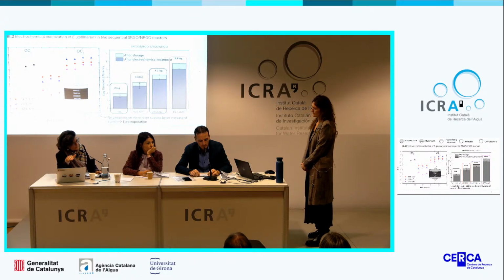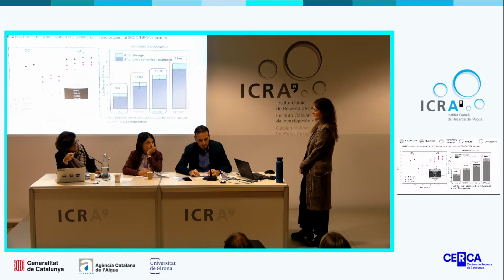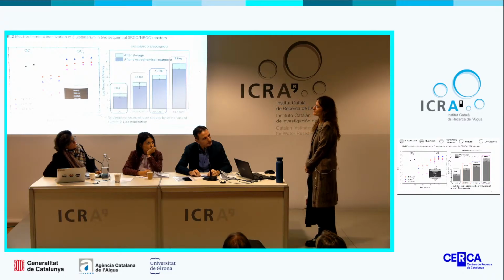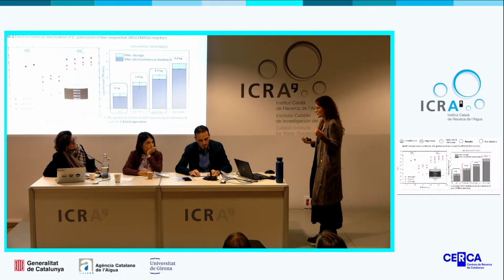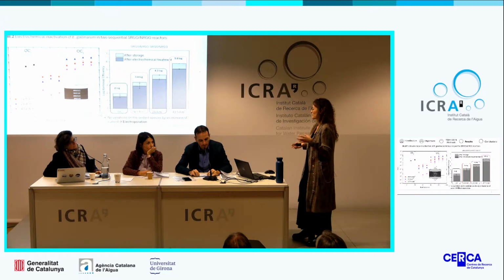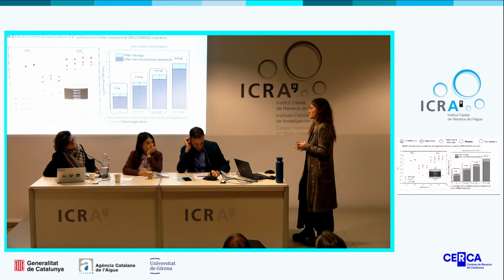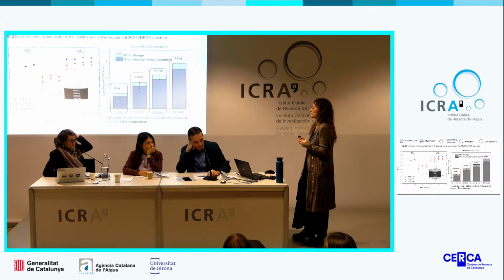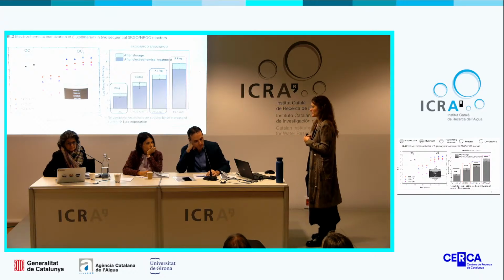Yes, to regenerate your material, you use methanol. Do you? Yes. Okay. Have you measured natural desorption? I mean, only with water or with the buffer solution? Or no? No, we didn't do it. We just tried this protocol, which was just a confirmation of the elimination, the degradation, but it needs further improvement because it was also used for those antibiotics which were really adsorbed onto the sponge. For the others, we couldn't see anything. So yeah, it was just a trial to confirm the differences between the removal.